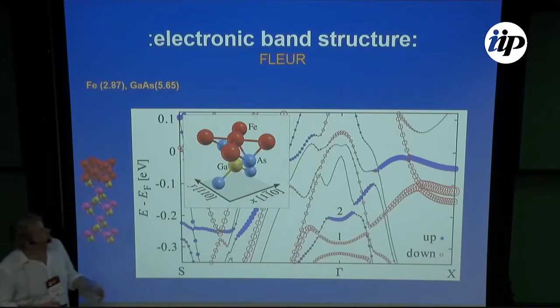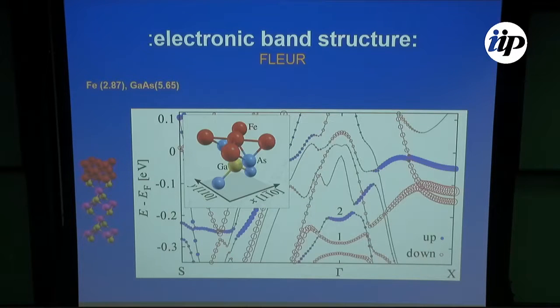But we figured it out for this particular system or for ferromagnetic semiconductors. And we could extract from the ab initio band structure, by playing with different magnetization orientations, the spin orbit fields at a particular momentum.